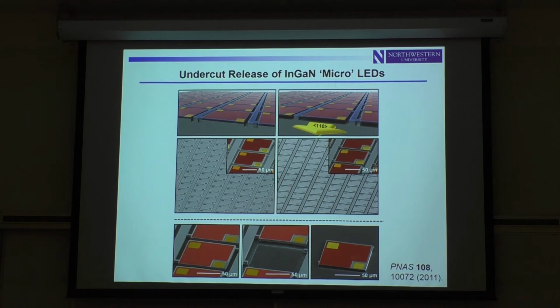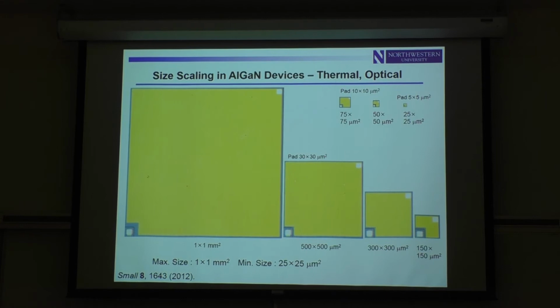The kind of release etching approaches that we use are related to those for silicon, a little bit different. But in any case, we can take active materials grown on silicon substrates, and then instead of using a dicing saw to basically cut up the whole wafer and then a pick and place tool to move the components around in the way that you would usually process LEDs, we can shave off the near surface of the wafer, just the active III-V materials, get rid of the wafer, and then manipulate these devices in various ways to allow their integration on any kind of substrate of interest at sufficiently thin geometries that we can just do lithographic patterning of metal instead of wire bonding to do the interconnects. And that turns out to be a critical feature. Instead of the lateral resolution of the devices being set by the precision of a dicing saw or a dicing laser, it is now defined by lithography, the photolithographic processes that are used in semiconductor manufacturing. So we can scale down to much, much tinier devices than are possible commercially.